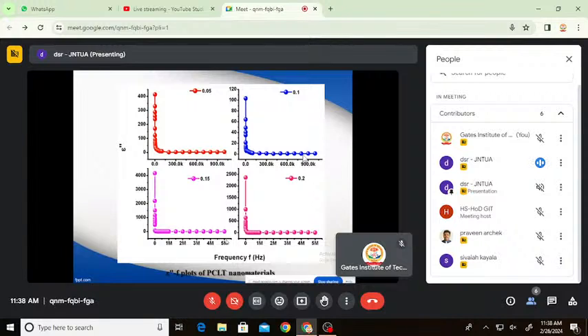But large epsilon dash and epsilon double dash values for the concentrations of 0.15 and 0.2 computed in the megahertz frequency range may be suitable for dielectric absorber applications at high frequencies.